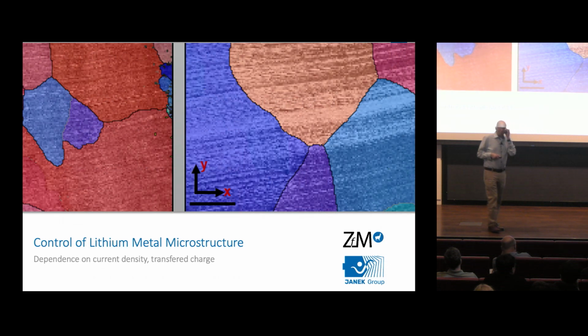Okay, now, at this point, let me have a brief summary saying the microstructure, we want to have a small-grained microstructure because then we have a better electrode that can achieve higher, faster kinetics because the grain boundaries are fast. But pure lithium tends to grow to large grains. So what shall we do?